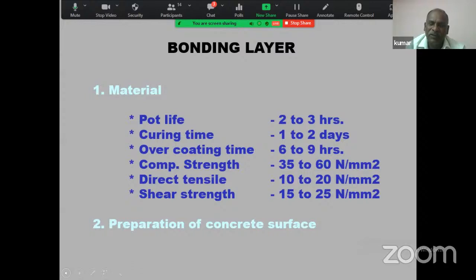If it is not an impermeable layer, then what happens? The new and old on both sides will have reactions. So in that case you have to have a proper bonding layer. The purpose of the bonding layer is, number one, it has to take up the new material and it should have a high bond between old and new concrete. And second thing, protection. So these are the two aspects for which you use the bonding layer.